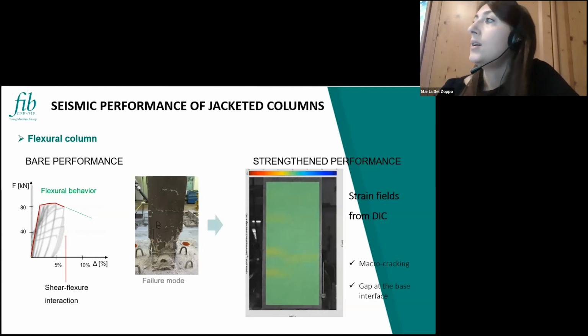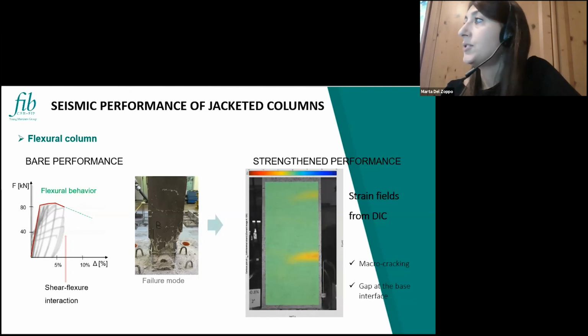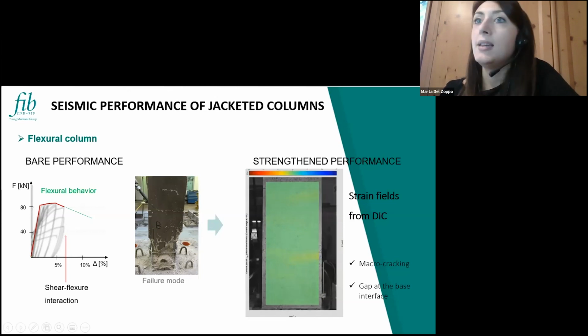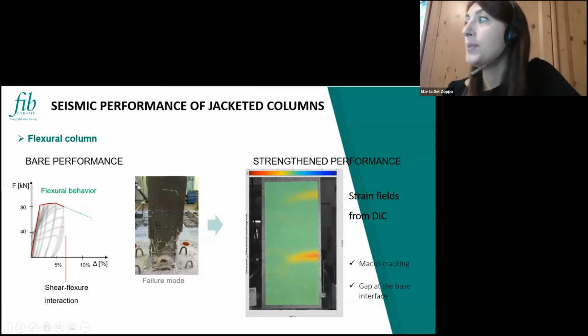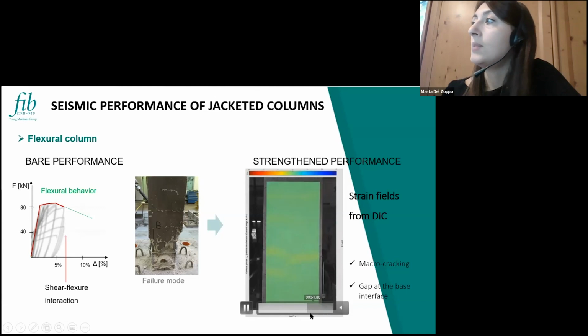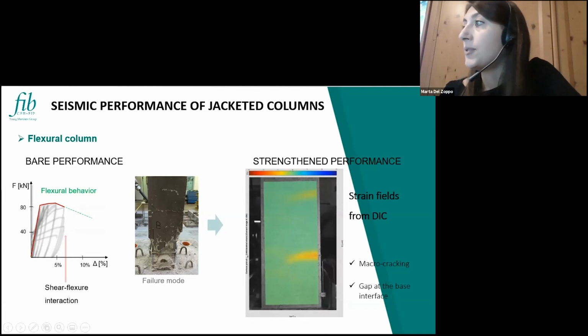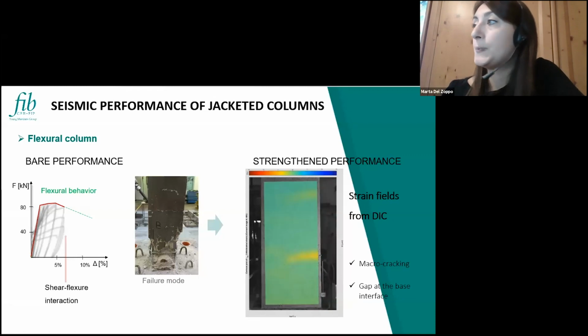Basically, looking at the strain fields, thanks to the digital image correlation, we can see how the strain fields are changing during the test on the jacket and how the tensile strain concentrations are localized near the cracks in the jacket. So we can still observe this macro cracking behavior of the jacket, of the FRCC material. And also we can note that a large gap is opening at the bottom of the specimen, at the interface between the jacket and the foundation block.